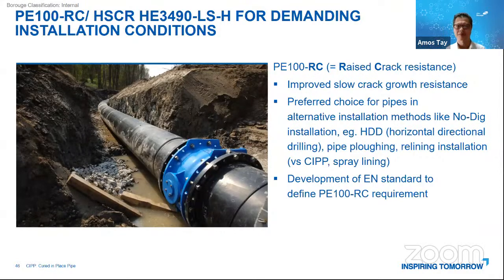But with this feature, this slow crack growth will be there, but it takes a longer time to grow through the pipe wall. This material is preferred for installations like no-dig, horizontal directional drilling, because you're going through the soil and you don't know what's inside the soil. There may be some hard stone that may be cutting the pipe when you pull the pipe through the ground, and also pipe plowing and other techniques.